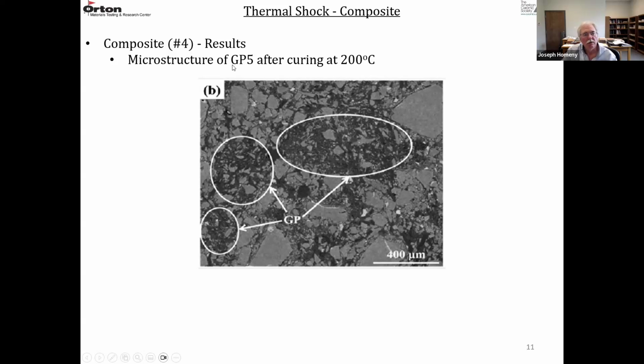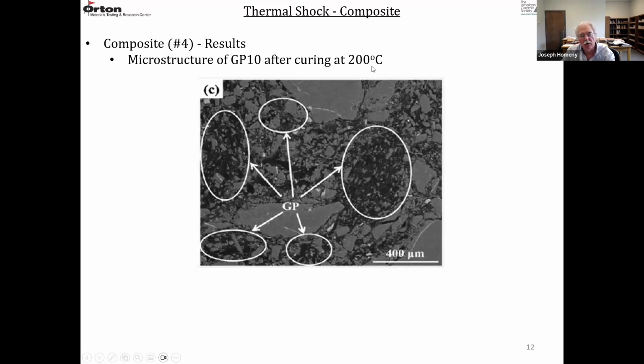And then this is the microstructure of the sample with GP5. So it had MgO carbon pellets, and these circled areas are the actual pellets. So you see some fine MgO particles, and then the rest is the resin graphite matrix that's been crushed. So the pellets show up and are outlined here. This is GP10 after curing at 200. So these regions here are the pellets in the matrix.